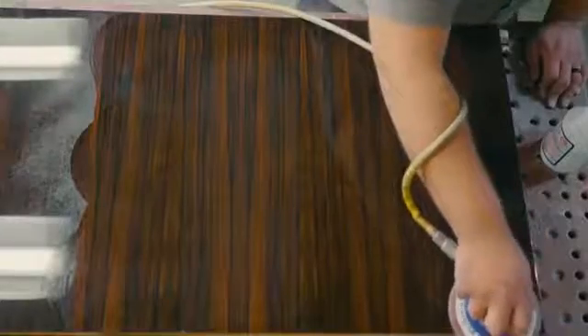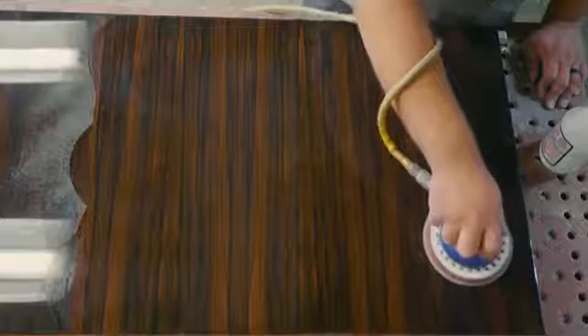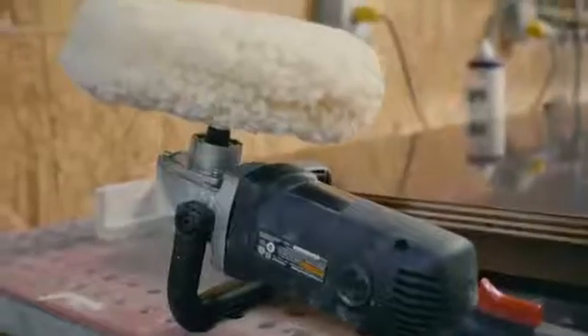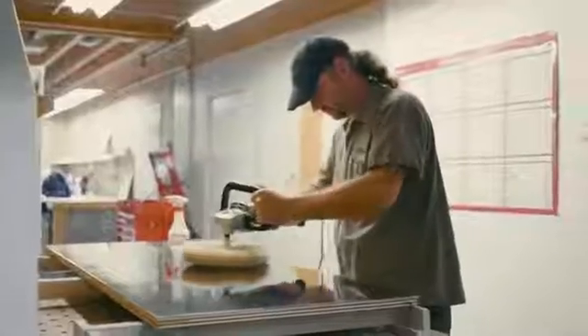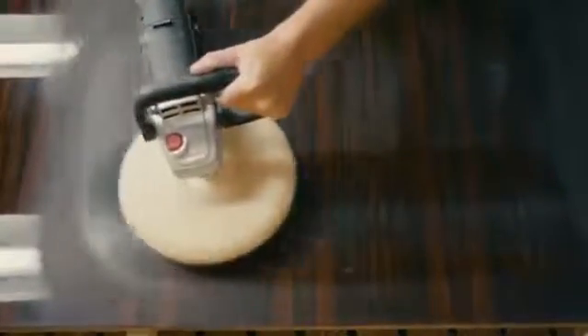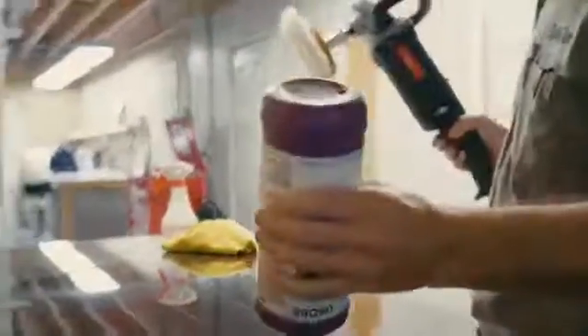Blue Sky Armor can be sanded, polished, and buffed with great success with standard sanding papers and equipment, and will polish to a high-gloss sheen. Initial cutting is managed with a wool pad and stage 1 compound. To finish buffing, use a foam pad with number 2 polish. Giving the panel a final quick buff with a lambswool pad will yield a mirror finish by following this simple process.